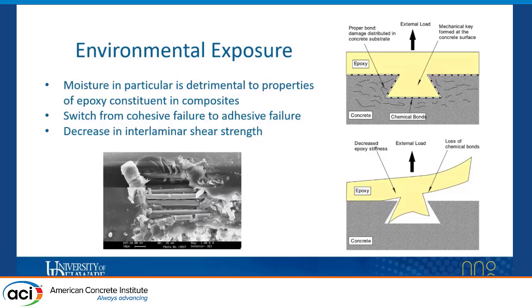There's a lot of existing research so far with respect to the effects of environmental exposure on CFRP concrete strengthened members. From the research that's been completed so far, it's been concluded that moisture is the most detrimental to strengthened members. In addition, it's also been concluded that the deterioration that's reported isn't necessarily deterioration to fiber-controlled properties, but rather epoxy-controlled properties.